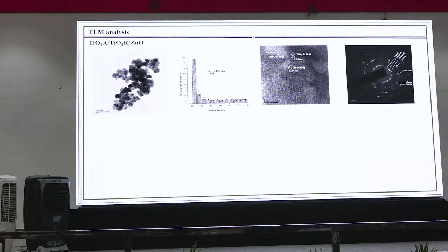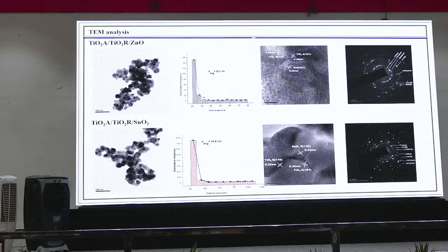Then we have done the TEM analysis just to know the particle size, because particle size matters a lot for the surface. And we also did the HR-TEM analysis, to identify whether the phases are there or not.